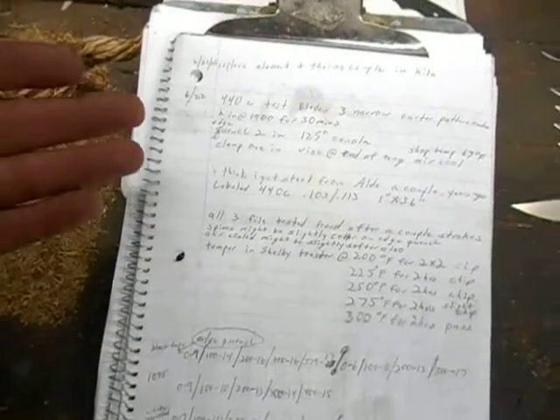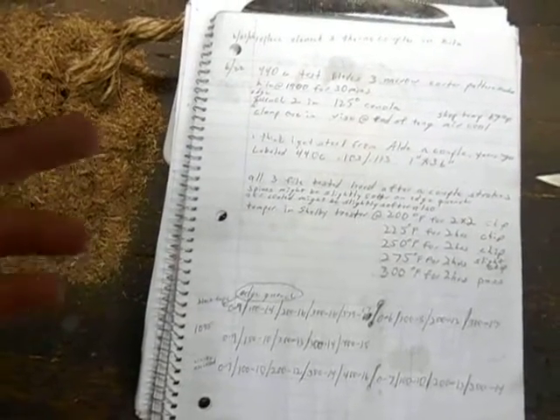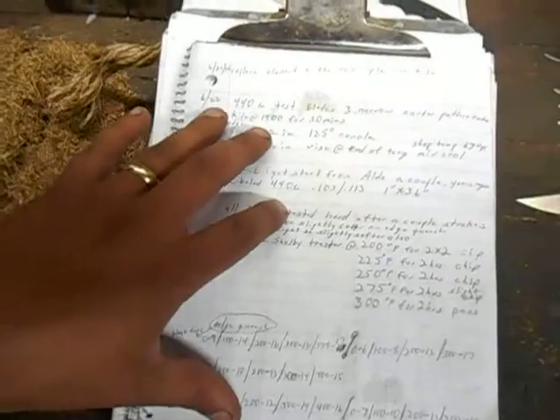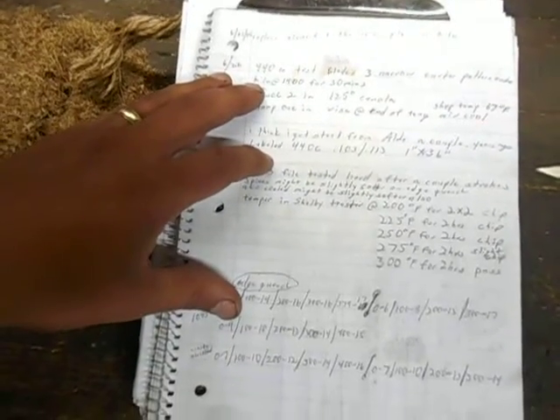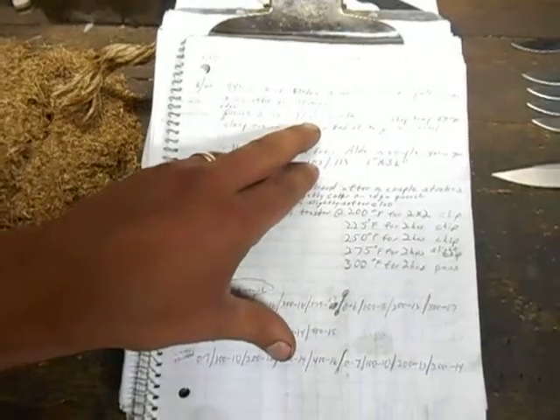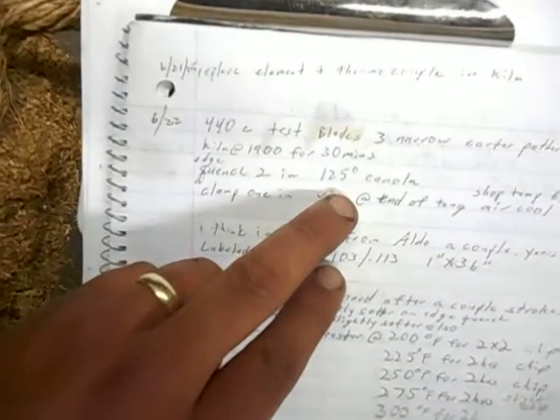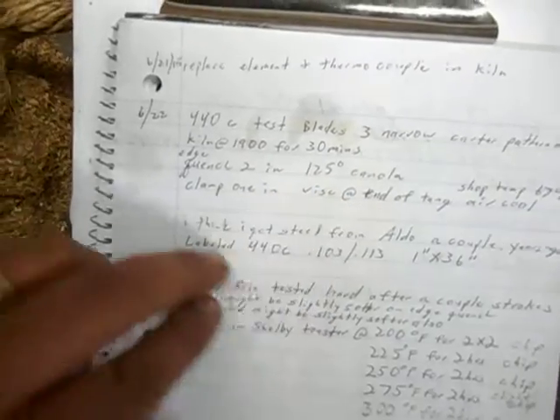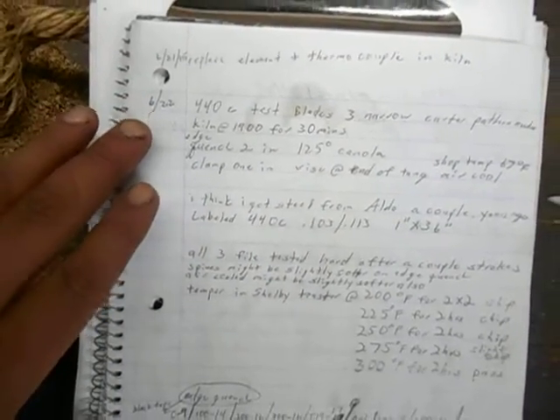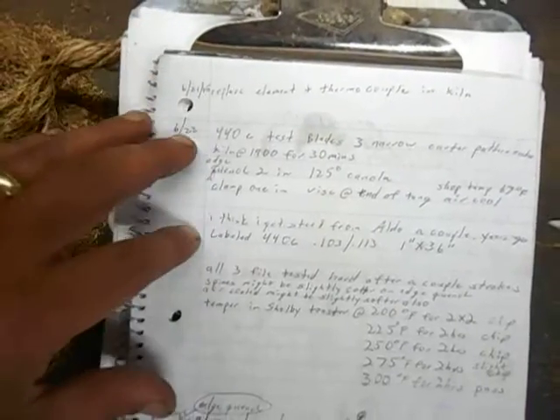The most common heat treat that I found on the internet was basically to bring your kiln up to, I think, 1875 to about 1950. Place the blades in there, keep the blades in for 30 minutes or so, and then oil or air quench the blades. I went ahead and used oil because when I ran this test, I had just finished heat treating a whole bunch of 1095 blades. I heat treat those in canola oil, and it had cooled down to 125 degrees. I'm mostly an edge quench kind of guy, so this first series of tests I did edge quenches on them.